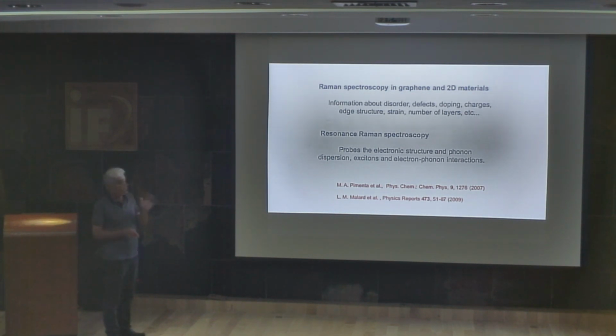Raman spectroscopy with just one laser line is very useful to study all kinds of materials, especially graphene and 2D materials, because we can get much important information about disorder, defects, presence of doping, charge, strain, the structure of the edge, and number of layers. It's very useful to get all those properties. But when we are able to have many different laser lines, tune the laser line, and follow the intensity of the peak as we tune it, that is what we call resonant Raman spectroscopy. Then we can also probe the electronic structure, the phonon dispersion, excitons, and mostly the electron-phonon interaction.